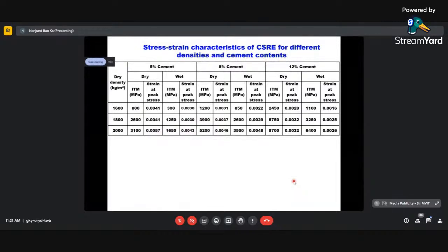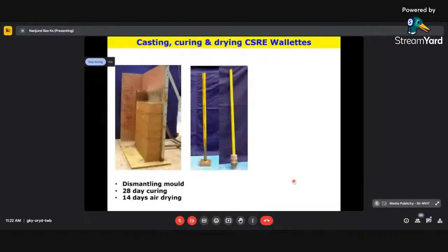This is again stress strain characteristics, for different cement contents, that is 5, 8 and 12%, and also for different dry densities, 1600 kg per meter cube, 1800 kg per meter cube, and 2000 kg per meter cube. What is the initial tangent modulus in the dry and the wet state, and the value of strain at peak stress for these three cement contents and for the three densities, for dry and saturated conditions. These are the numbers. All these things were generated through tests in the IISc Department of Civil Engineering.